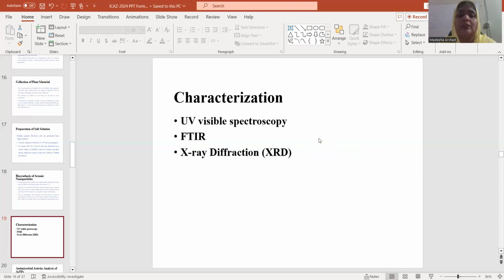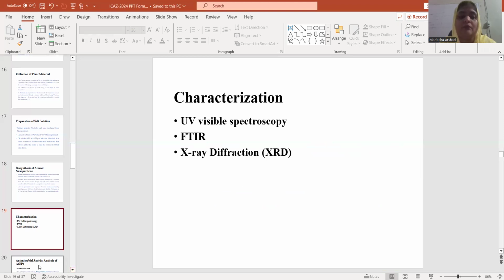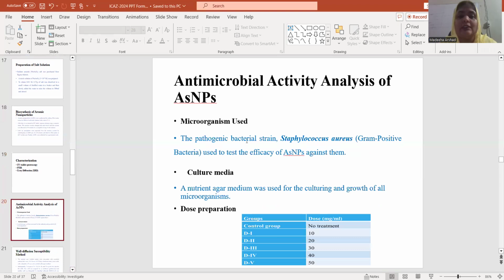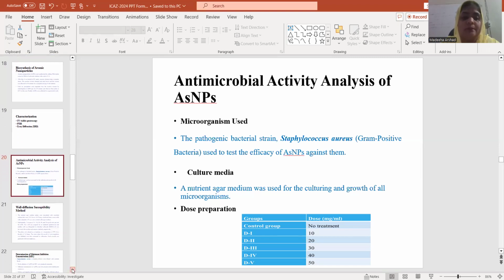Characterization was done using UV visible spectroscopy, FTIR, and XRD. While antimicrobial activity analysis of arsenic nanoparticles was done using the pathogenic bacterial strain Staphylococcus aureus, which is a gram-positive bacterium, and it was used to test the efficacy of arsenic nanoparticles against them. Those were prepared at different concentrations of arsenic nanoparticles like 10 mg per ml, 20, 30, 40, and 50 mg per ml in respective dose groups.